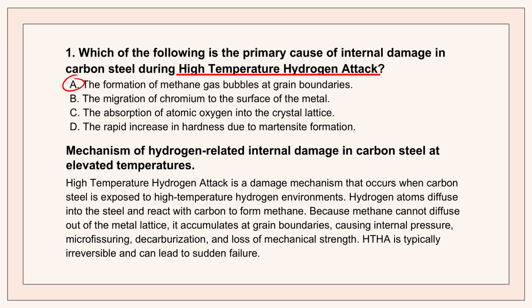And this is where the structural time bomb starts ticking, because methane molecules are way bigger than the hydrogen ones they replace. Way bigger. And suddenly they're too large to get back out of that dense metal lattice. So they're trapped. Precisely. It's a self-trapping mechanism. This trapped high-pressure methane gas builds up along the grain boundaries, which are the weak points of the metal structure. It's like inflating thousands of tiny balloons inside a solid block of steel. That's a great way to put it.